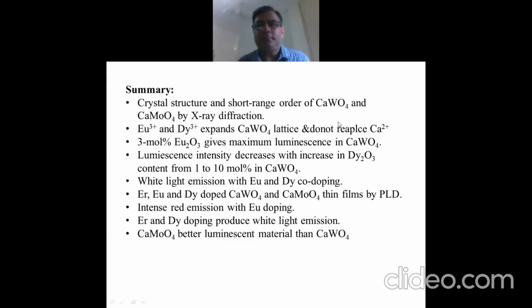Although there are many dopants, why have you doped dysprosium and europium only? Actually, dysprosium is a white light emitting material. It emits strongly in the green part of the electromagnetic spectrum, and it also emits somewhat in the blue part of the visible light spectrum, whereas europium emits most strongly in the red part. So if you co-dope with dysprosium and europium, you get a material which is a good white light emitter. So you get blue and green emission from dysprosium ions and red emission from the europium ions. So the net result is that the sample is a white light emitter.